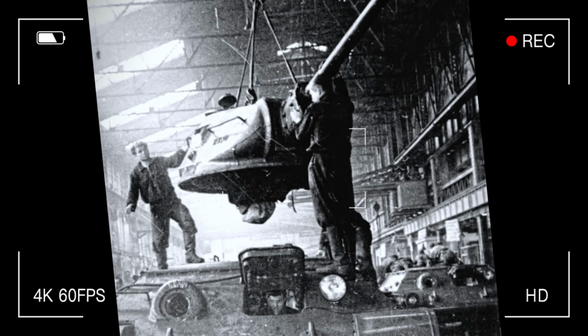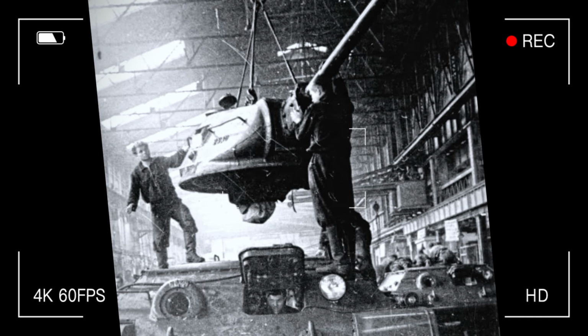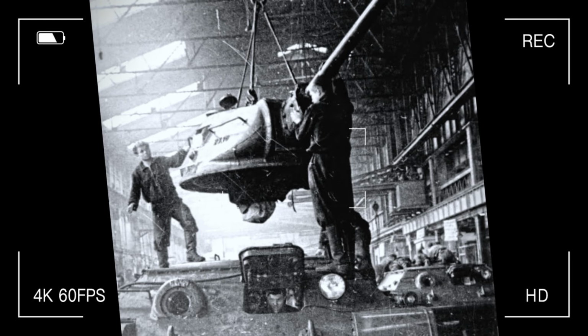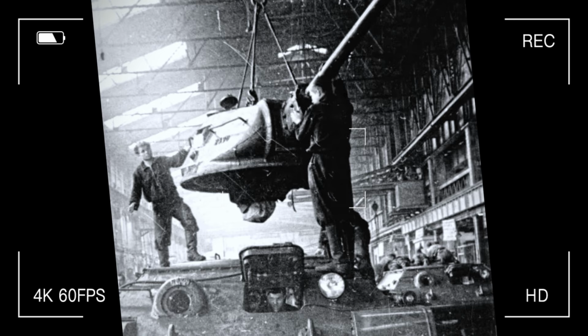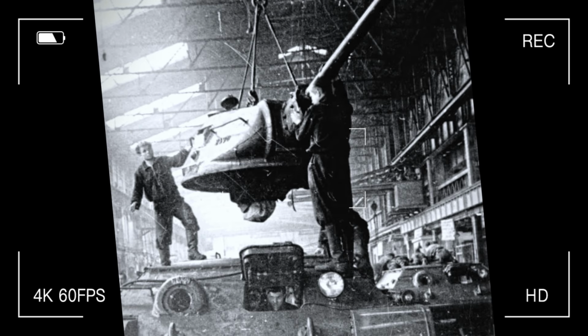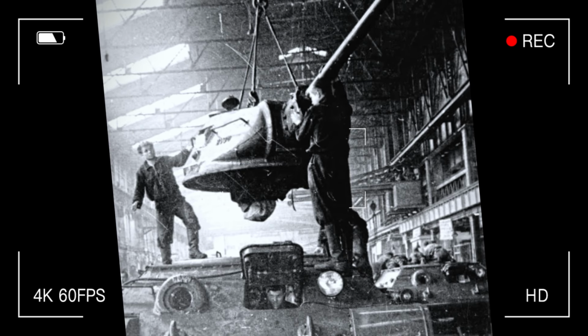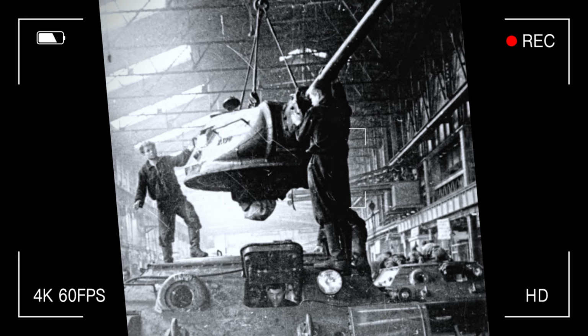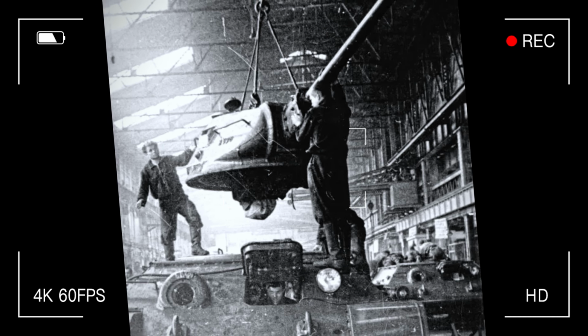But this created another problem. Chromium was essential for achieving a fibrous fracture, a key indicator of quality armor. If chromium was too low, less than 1.3%, the armor could behave in a brutal way when hit by a shell. It was a delicate balancing act.